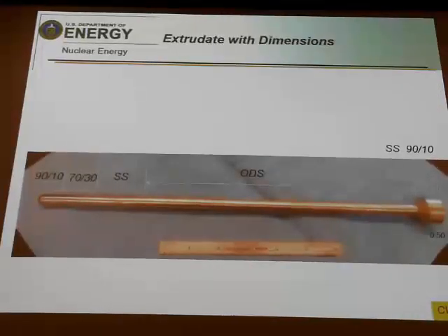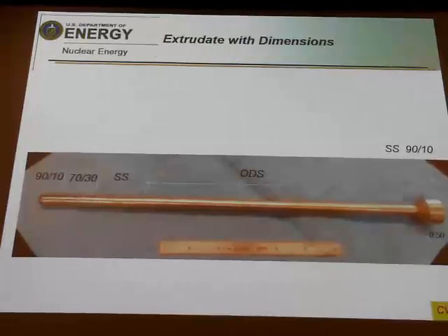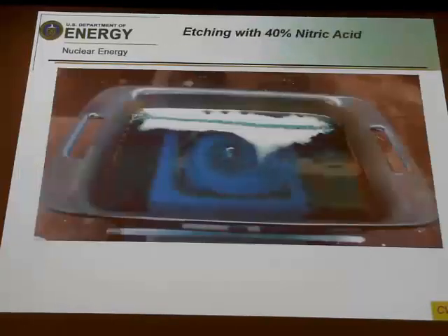I can tell you that even after you get done with the extrudate, this is the Oxide Dispersion Strengthened steel area. It's got all the extrudate over it. So you have to go through etching it with 40% nitric acid for about 2 or 3 days. And once you've etched off the material, then you end up with a nice tube. This is about a 10-inch long tube that was extruded out of Oxide Dispersion Strengthened steel. And we can do some tests with that. We can look at whether we've got a uniform dispersion of oxides throughout. We can look at what the texture is. So it's nice from a research standpoint, but it's a difficult way to get there from an industry standpoint if you want to make something affordable.